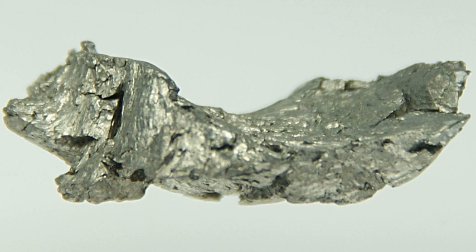Gadolinium-153 is produced in a nuclear reactor from elemental europium or enriched gadolinium targets. It has a half-life of 240 plus or minus 10 days and emits gamma radiation with strong peaks at 41 keV and 102 keV. It is used in many quality assurance applications, such as line sources and calibration phantoms, to ensure that nuclear medicine imaging systems operate correctly and produce useful images of radioisotope distribution inside the patient. It is also used as a gamma ray source in X-ray absorption measurements or in bone density gauges for osteoporosis screening, as well as in the Lixiscope portable X-ray imaging system.